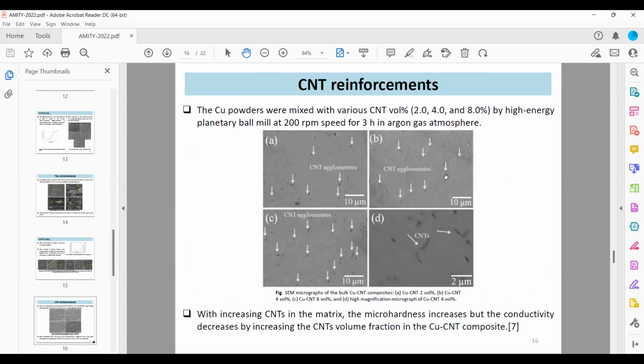Carbon nanotubes. Addition of carbon nanotubes to copper refines the grain size, and when the nanotube percentage increases, they form clusters, and the number of agglomerates increases. As CNT has a very high van der Waals force, they have a strong tendency to cluster and agglomerate. Hardness of the nanocomposite increases just up to a certain point. Also, the electrical conductivity of the nanocomposite decreases because, due to agglomeration, blocking of particles in the matrix occurs.